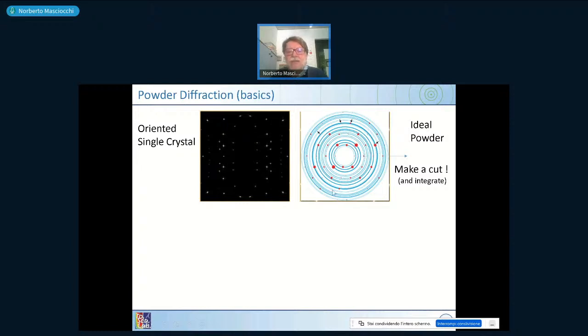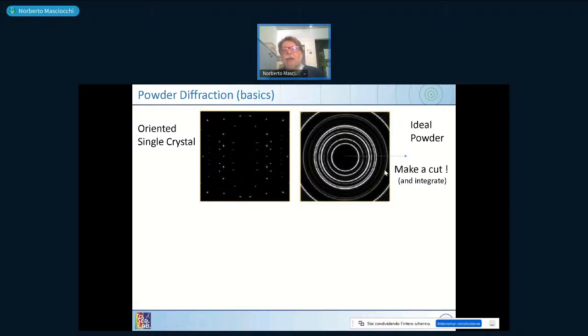And this set of circles is redundant because every point here at the bottom is equal to the one at the top, equal to the left. So it's necessary only to make one sampling from the center to any direction, a cut, basically. If you make it horizontally, vertically, or in any other direction, these give you equal information. And then you can measure what its intensity is from the center to higher angle, because remember, if this is a screen position perpendicular to your beam, then the farther you go, the higher is the angle you measure.